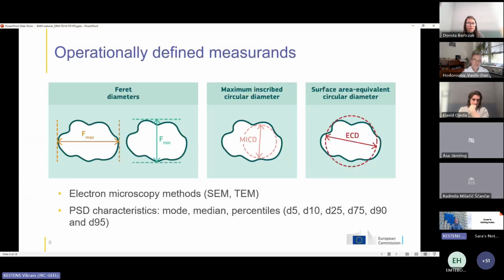And for the measurements of these particles, we looked at very specific measurements for electron microscopy, because basically electron microscopy is one of the few methods available that can really measure the constituent particles inside agglomerates and aggregates. The measurements that we have been looking at were basically the Feret diameters, both the Fmax and the Fmin. We have also been looking at the maximum inscribed circular diameter and the equivalent circular diameter.